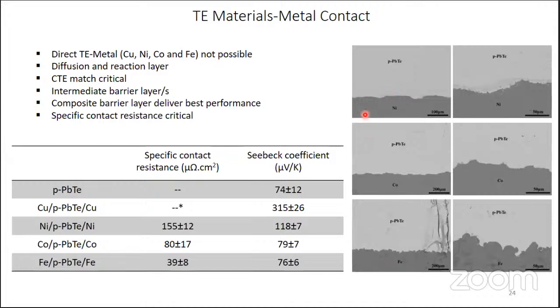Directly contacting resulted in highly unstable contacts. There is an interdiffusion between these two during the operation. You can see that the specific contact resistance is very high, and the Seebeck coefficient of the starting material is 74, so this increases to very high. It means the material started diffusing into lead telluride and poisoning the lead telluride. So the direct contact of any of these electrode materials to lead telluride will not result in any good, stable metal semiconductor joint.